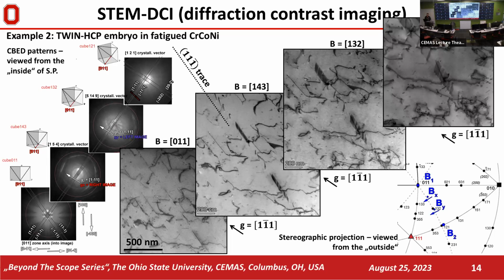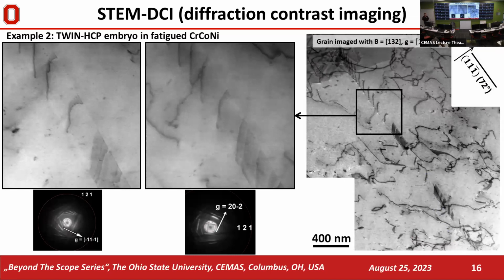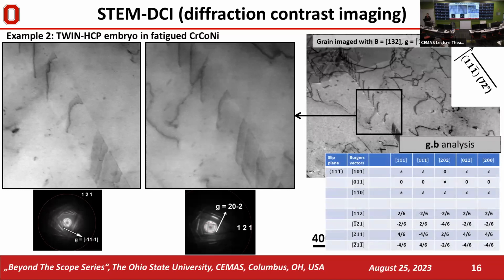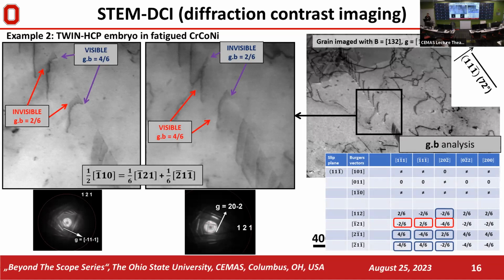So here, on the map of reciprocal space on the left side of the slide, you can see that you have plenty of opportunities to use different Gs to perform g.b analysis, or to tilt your crystal to different Gs to get information about the arrangement of defects and their interactions in this specific area. One of the examples here, we want to find out what the individual dislocations in the slip band are. Similarly to conventional TEM, in STEM here we do a 2-beam diffraction condition, different Gs, different tilts. We can do g.b analysis, a table of visibility and invisibility conditions, and we can figure out what kind of Burgers vector these partials have, forming dissociated 1/2 110 dislocations. So this is very complementary to CTEM.